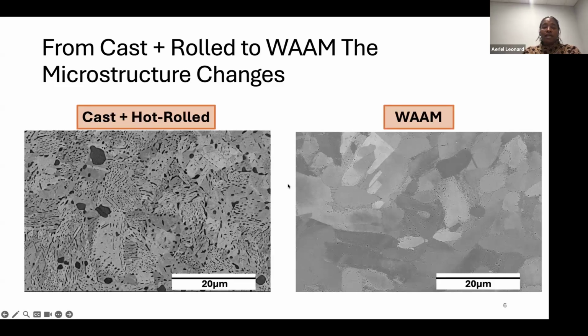Another thing you see are these lamellar type structures called kappa 3. Kappa 3 is an iron-based incoherent phase in the material. And then you can see kappa 2 here, which are these larger globular phases that are also iron-based. And then there's kappa 4, and kappa 4 sits within the matrix of the material.